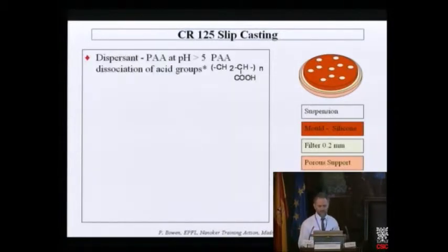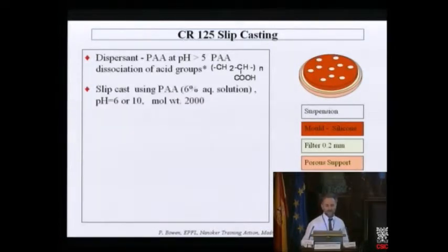Typical dispersant used is polyacrylic acid, where we have our carboxylate groups at pHs greater than 5 or 6. These start dissociating, so we can have electrosteric dispersion. You can slip cast at pH 6, pH 10, like I said, the molecular weight. We're using about 6% of this polyacrylic acid. When we have a high surface area, normally we need about 2 to 3 milligrams of polymer per meter squared of powder to disperse. When we have 100 meters squared per gram, we need a lot of polymer. You can get away with a little bit less than 6%, but this is what we ended up using.